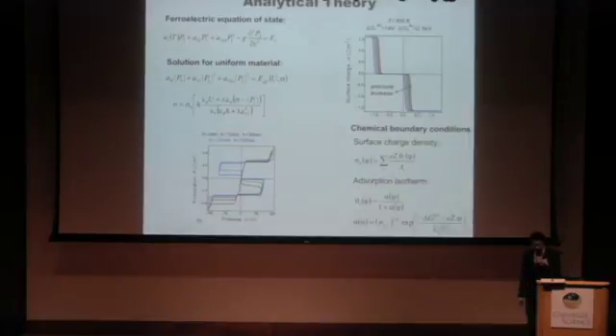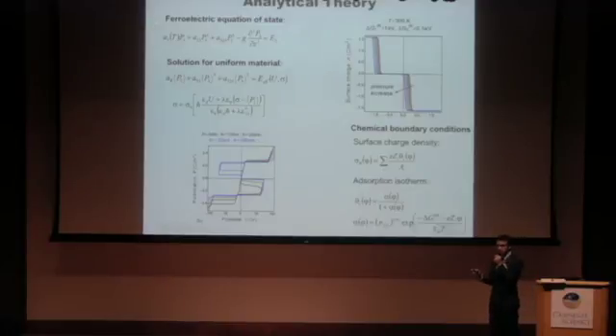So how do we actually try to model this? We take our standard ferroelectric equation of state, which is shown here. This is just the standard ferroelectric equation of state, and we don't do anything to it. We don't add any terms to it. All we do is change the boundary condition. So the boundary condition now is, instead of the electronic screening boundary condition, a chemical boundary condition. That's given by this surface charge density here.